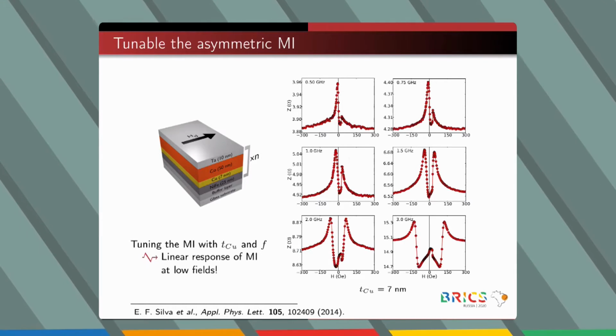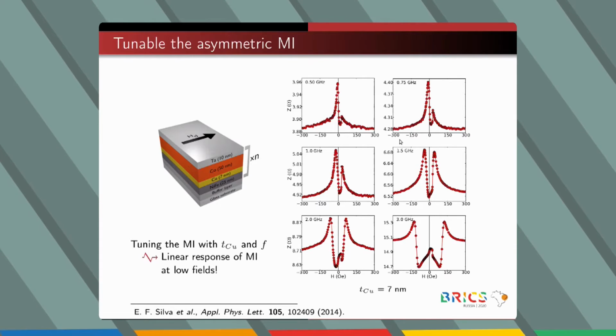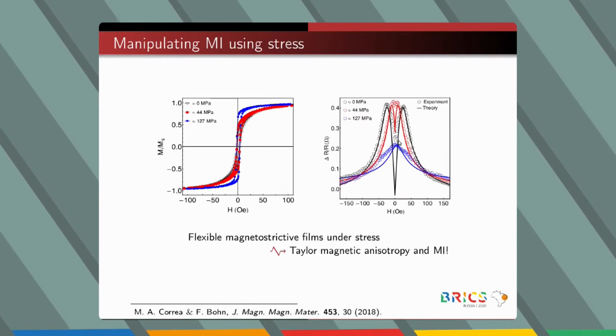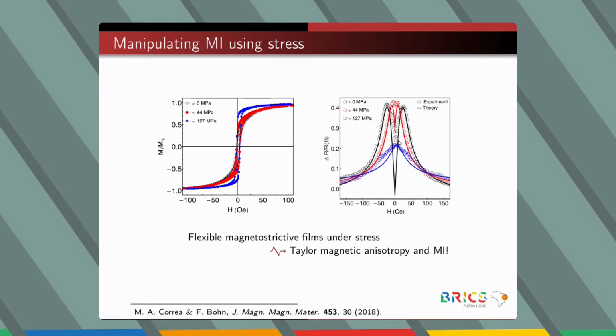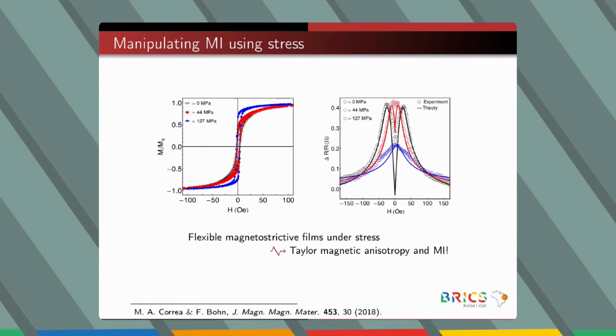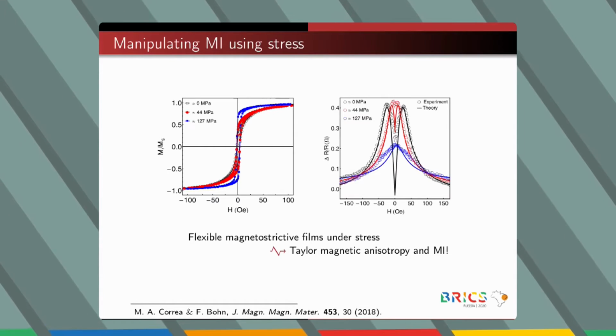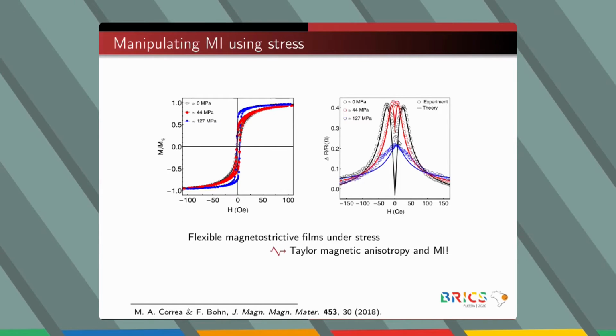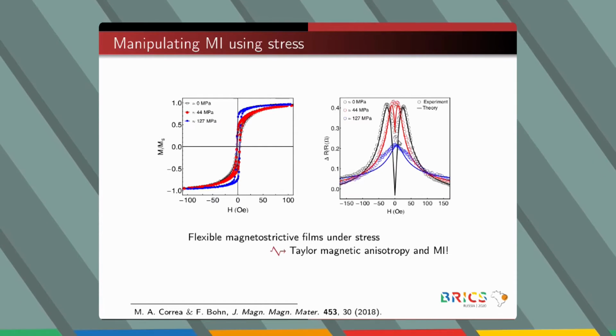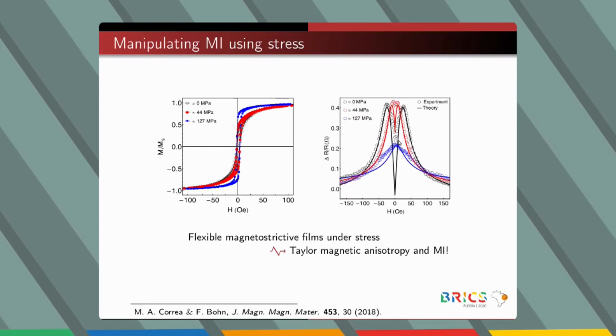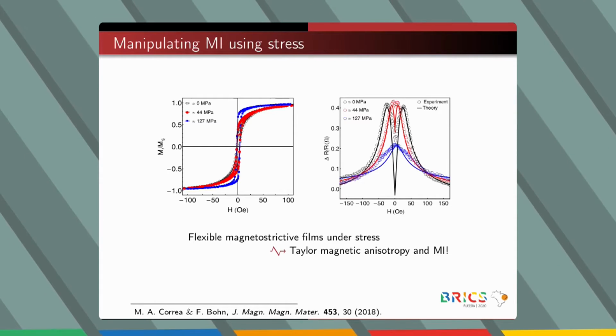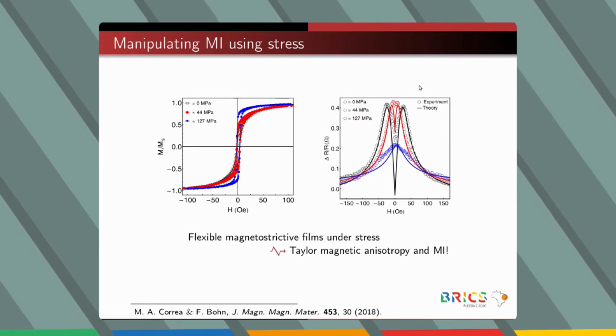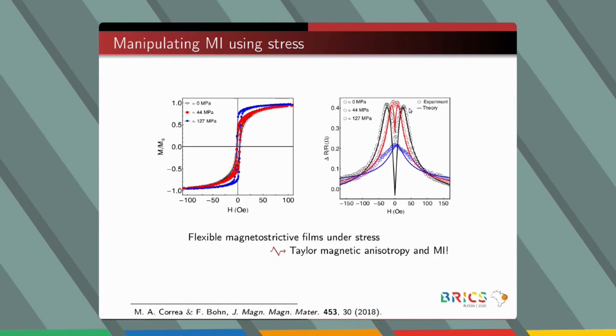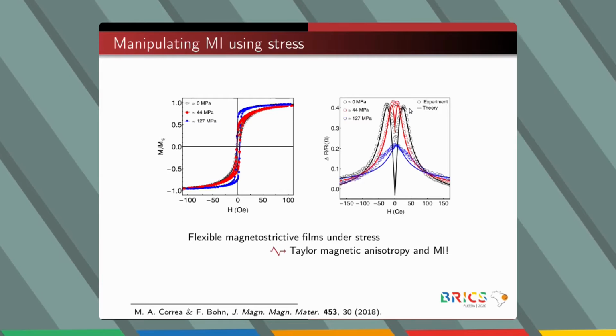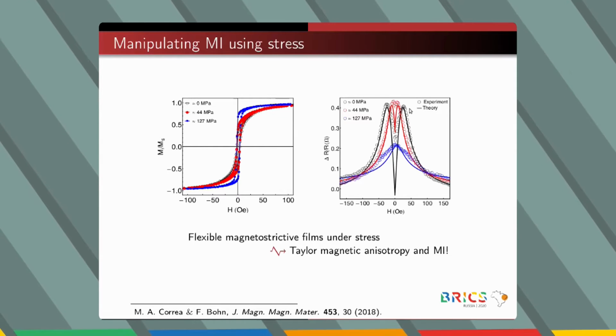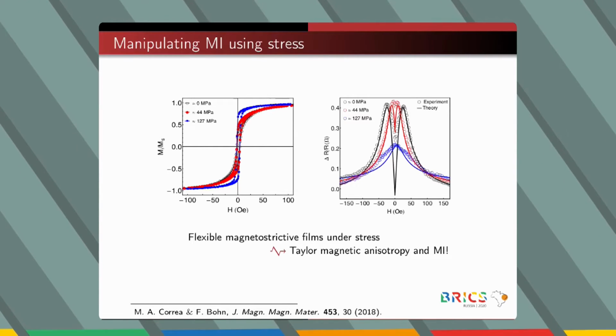or experiment parameters. In another work, we manipulated the magnetic properties of materials by applying stress to magnetostrictive films grown onto flexible substrate. The changes in the magnetic properties are directly reflected on the impedance response. Observe the agreement between experiment and theory, which allow us to envision the use of such samples in flexible devices.